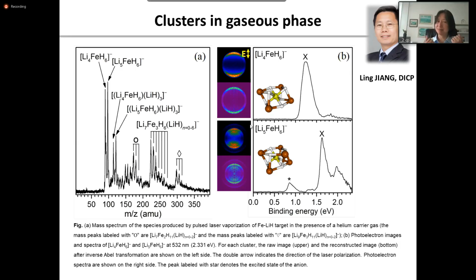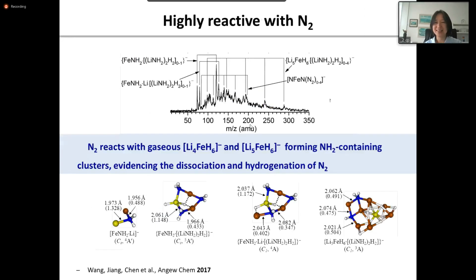This gives us the idea that those species probably have a chance to form on the surface, because the surface has unsaturated states, and it resembles to some extent a gaseous phase state. So for those bulk phase unstable hydrides, we probably have a chance to form them at the surface. We thought it could be a surface species, but now we investigate it in the gaseous